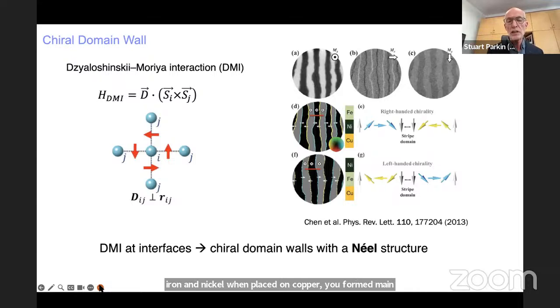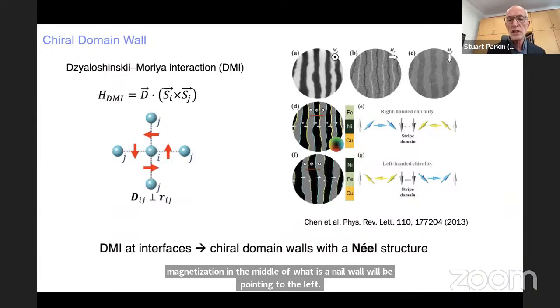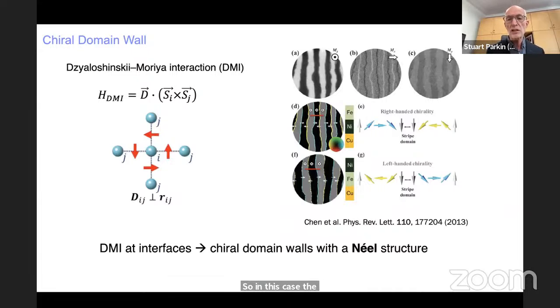And as you can see in this cartoon, this means that when, for example, iron and nickel are placed sequentially onto copper, in this case a single crystal, the magnetization rotates from an up to a down direction, and the magnetization, as you can see, will point in this blue direction to the right. The magnetization, when it rotates from down to up, the magnetization in the middle of what is a Néel wall will be pointing to the left. So in this case, the magnetization rotates in a plane perpendicular to the wall itself. On the other hand, if you reverse the sequence of nickel and iron layers, so the iron is grown first on copper, what this group found was that the chirality of the domain walls would change.